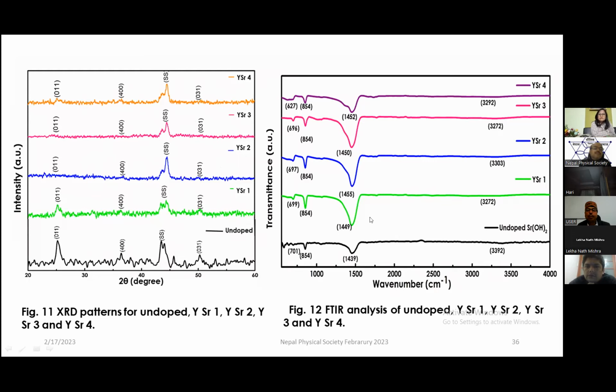Now we come to the FTIR. One can see a peak at 701 centimeter inverse for the undoped strontium hydroxide. This peak is shifting to the left side, which indicates that red shifting is taking place. Why is this red shifting taking place? Because of the creation of defects as a result of the yttrium doping. So if you are doping yttrium into the strontium hydroxide, it will create some defects.